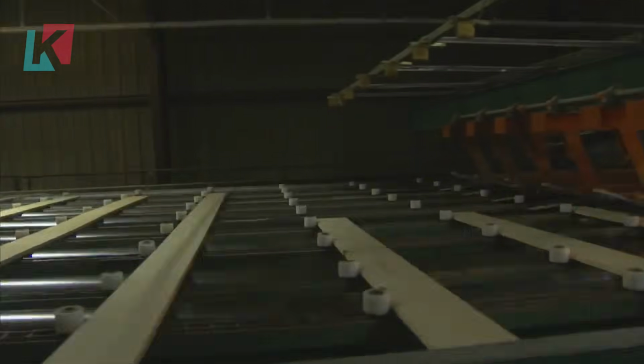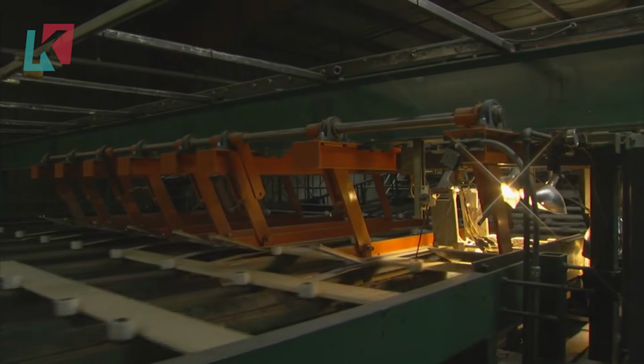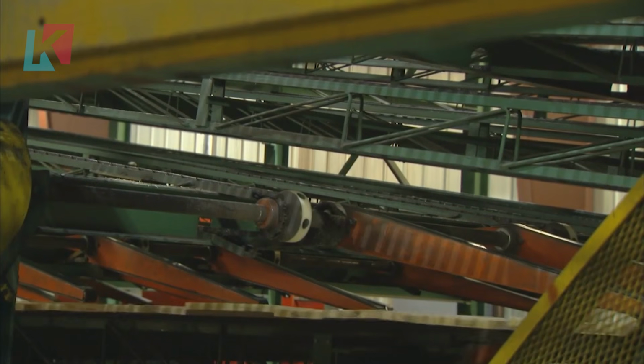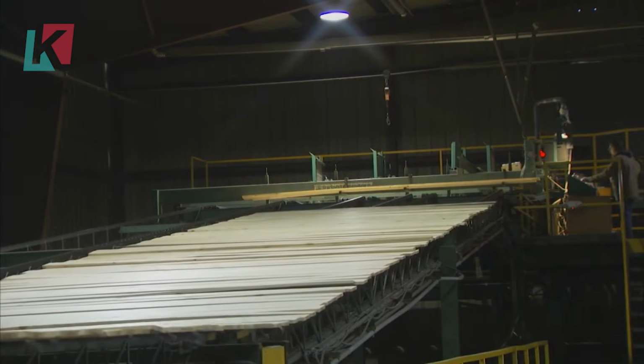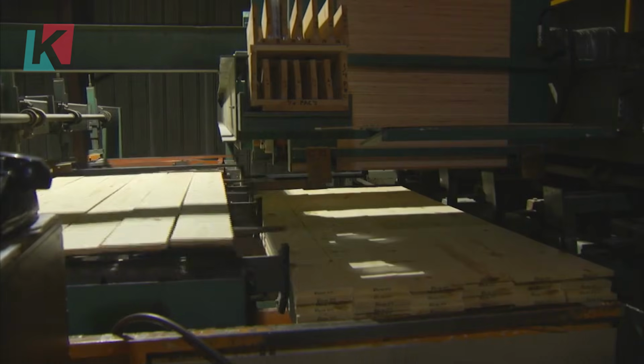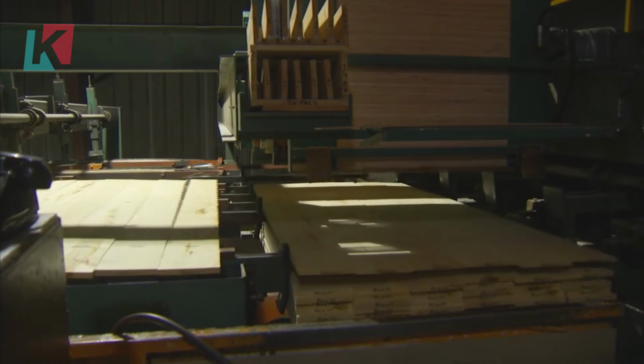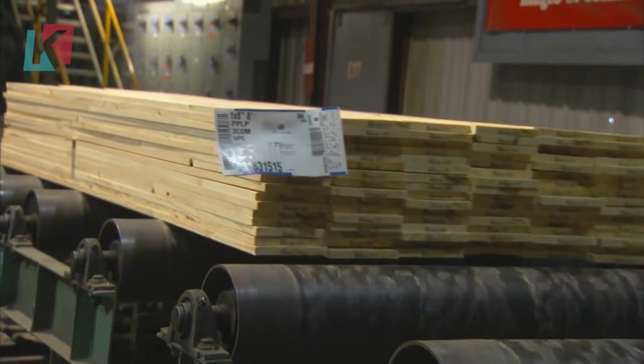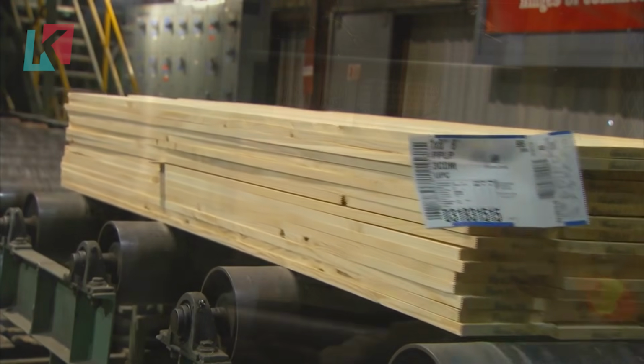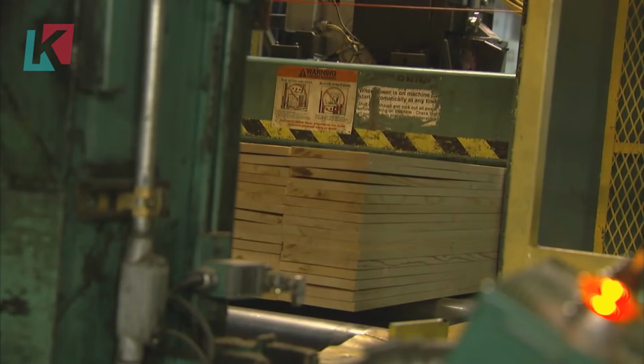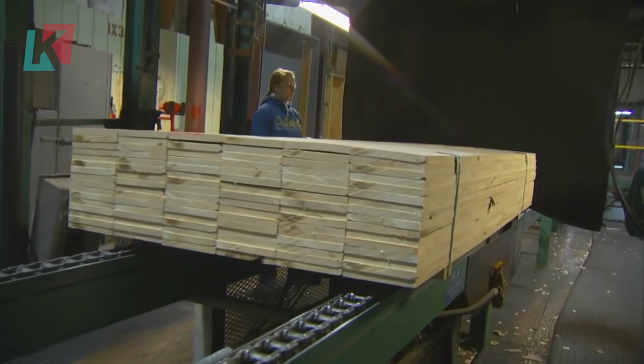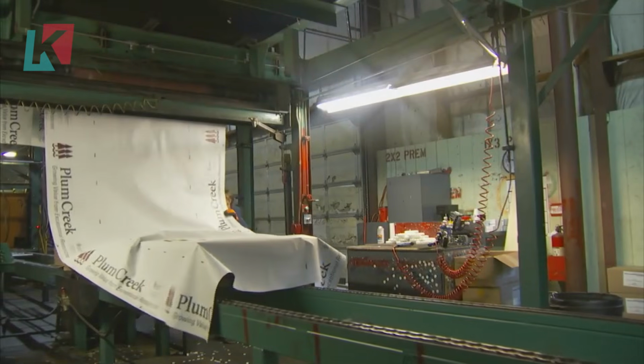The continuous press subjects the mat to temperatures of 400 degrees Fahrenheit and pressures exceeding 600 pounds per square inch. As the mat travels through this press, which can be over 100 feet long, the resin cures and the fibers bond together to create a panel that's denser and more stable than most natural woods. The precision of this process is remarkable. Temperature and pressure are controlled to within fractions of degrees and pounds per square inch.